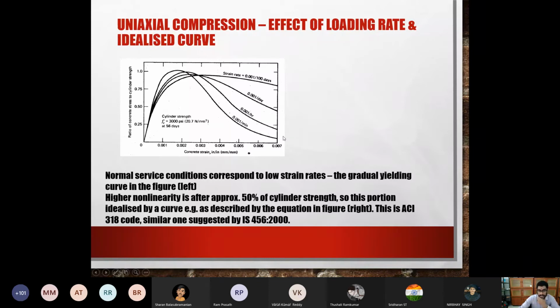But the one that we use in general for testing, when you do a test, we cannot load at even this rate. It's going to take forever even if you load it at 0.001 per hour. So this is the standard, the bottom curve. This is the standard testing curve which you will get if you actually test it. So normal service conditions correspond to low strain rates.